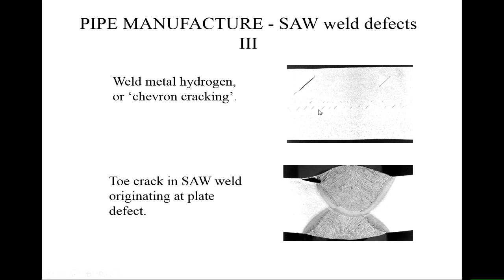We talked about hydrogen cracking. So if you weld in very wet environments and you don't dry out all your consumables and things like that, if your flux was wet when it was applied, which might happen if your factory leaks and somebody leaves the door open, forklift truck going in and out all the time, then you can get hydrogen cracking. And you can see there's a lot of these chevron cracks near the center of the plate, and then there's some near the edges. So there was probably some segregation in the center of the plate, which made it slightly more susceptible to hydrogen cracking than around the edge. And you can see the hook cracks on the end here, just to show that it's hydrogen cracking.